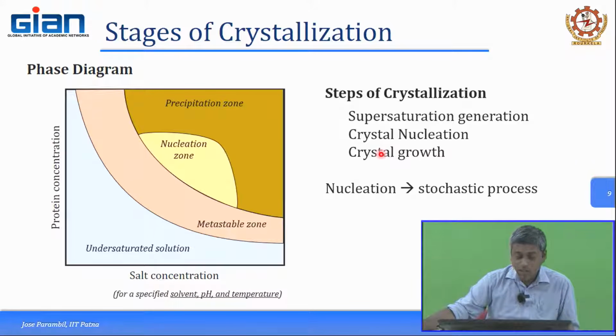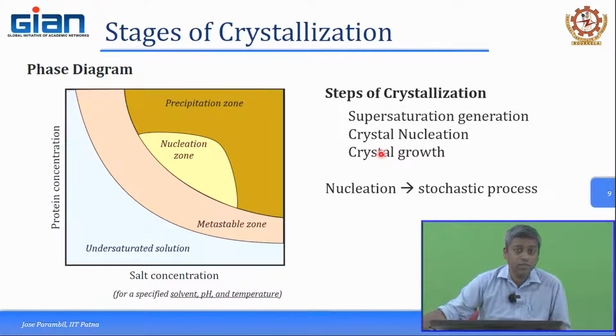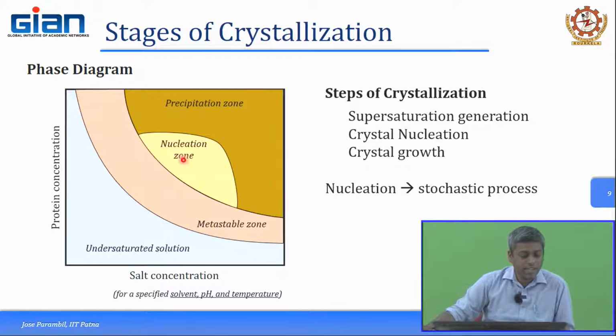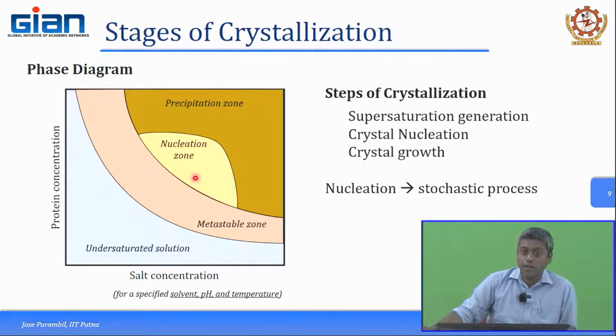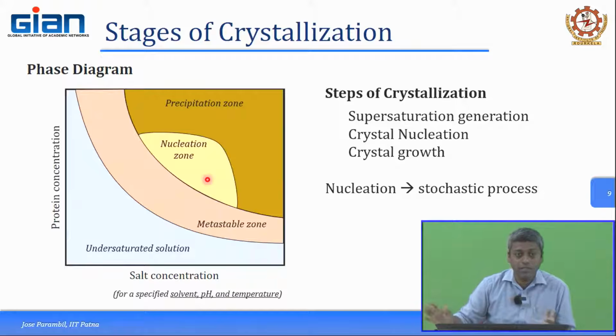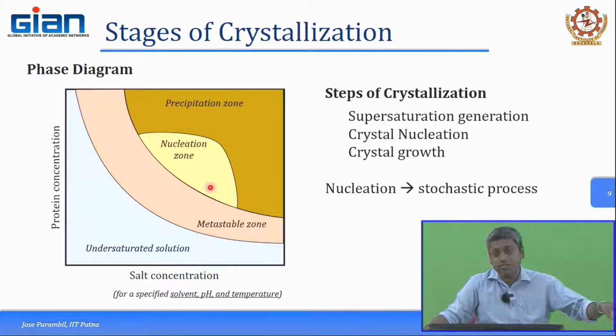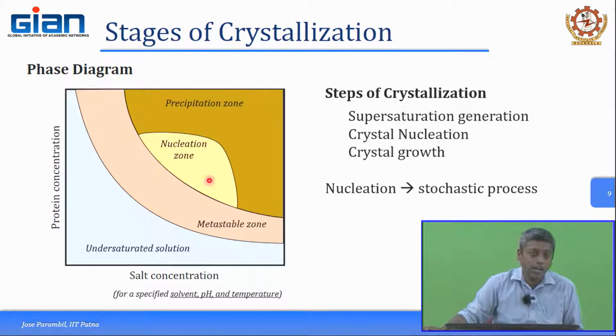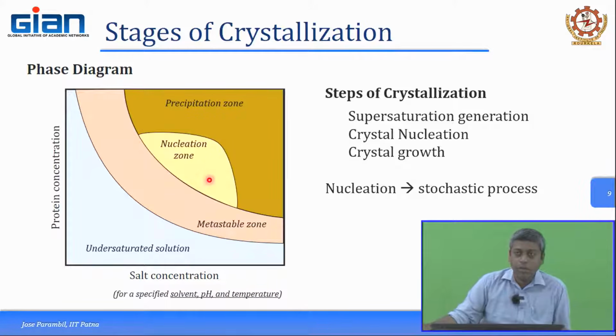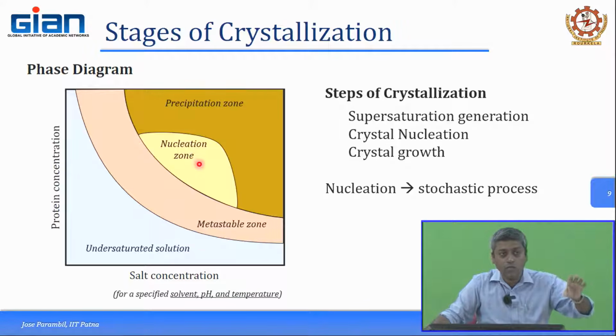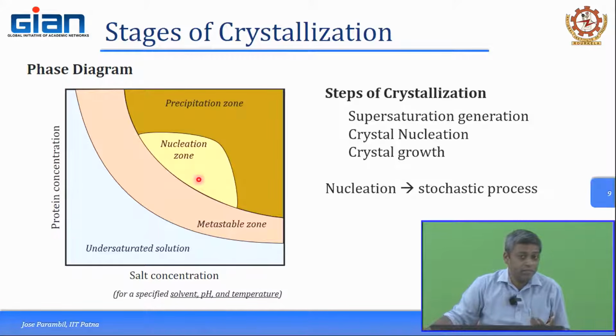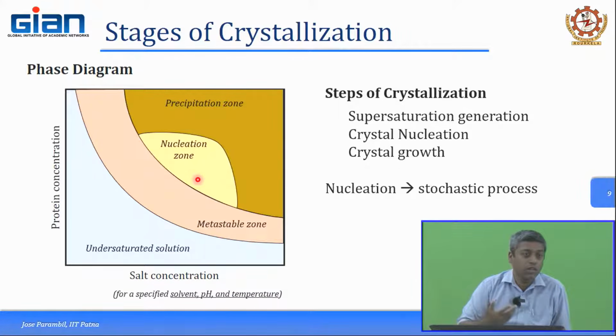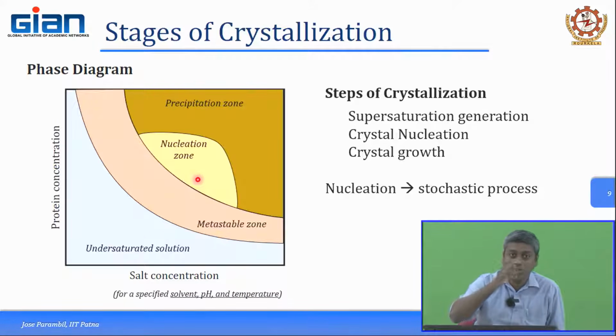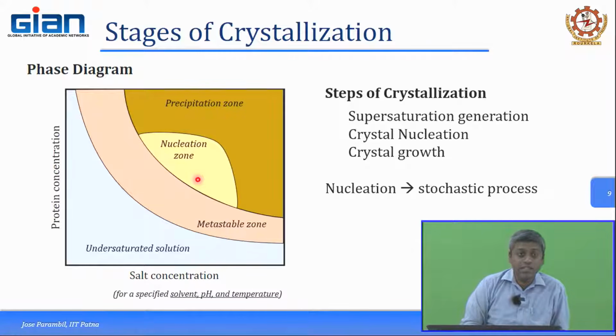Now, the major challenge as far as the operation of the crystallization system is concerned is that we say okay, it nucleates here, this is the nucleation zone, but nucleation is a highly stochastic or probabilistic phenomenon. In the sense, let us say you keep 10 systems to study at the same time, following the same conditions, and you make sure that all of them are within this nucleation zone. Even then, maybe 2 of them crystallize, you see the crystals in 2 hours or half an hour, 2 others take maybe a few more hours, 2-3 of them crystallize overnight, by the next day you come and it has crystallized, and a few of them might not even crystallize after a few days.